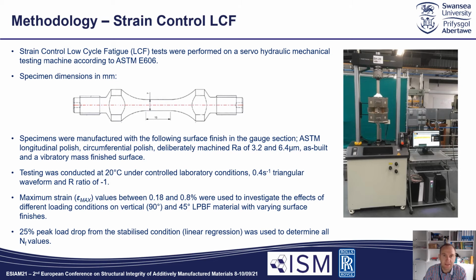So on to the mechanical testing. In this research, the specimens are subjected to strain-controlled LCF testing in accordance with ASTM E606. The specimens are manufactured in the 2 build directions and finished with a series of different surface finishes on the gauge section. This included the ASTM longitudinal polish, a circumferential polish, deliberate machined finish with an Ra of 3.2 and 6.4 microns, a vibratory mass finish, and also a series of specimens were retained in the as-built condition.